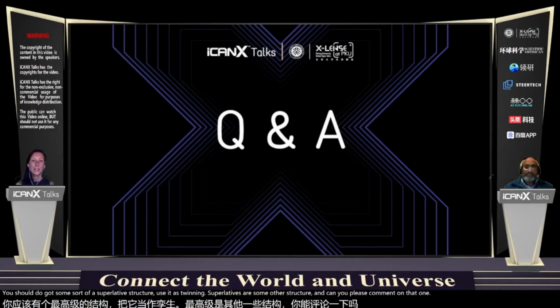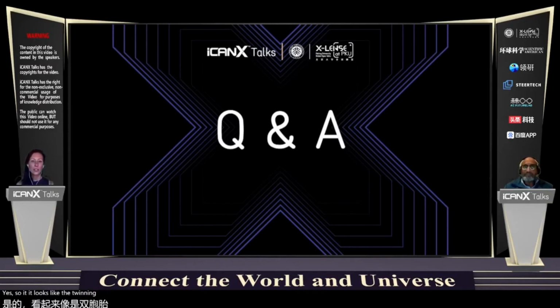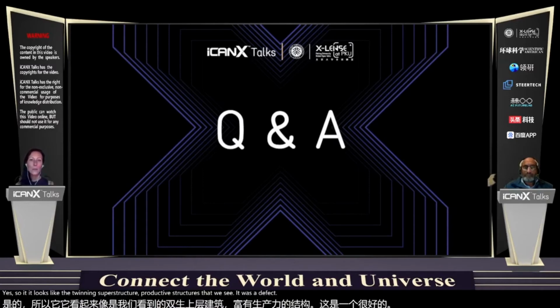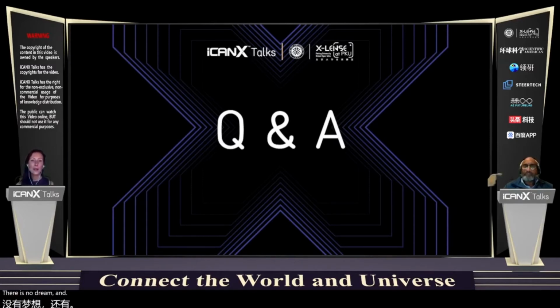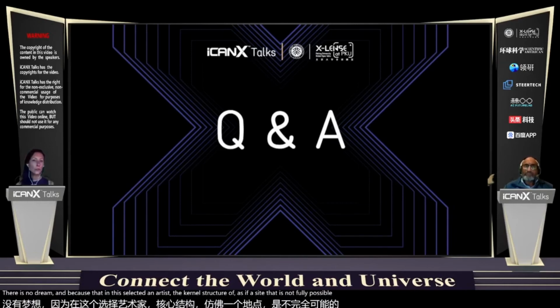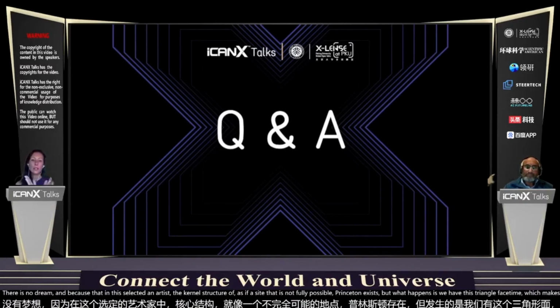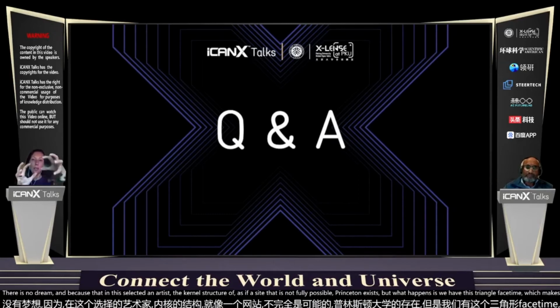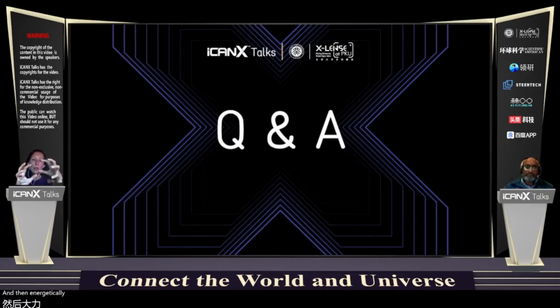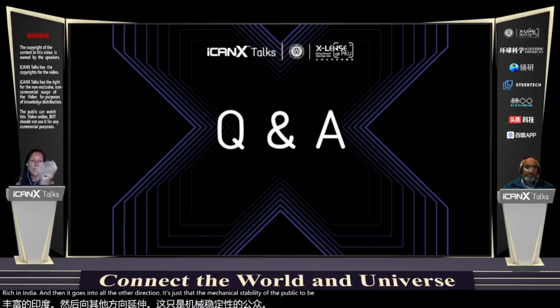Yes, so it looks like the twinning superlattice structures that we see with the III-Vs. There is no twin, because in this tetragonal structure of the zinc phosphide, there is no twinning possible. Twins don't exist. But what happens is we have this triangular facet, which makes the wire increase in diameter and the droplet becomes unstable. Then energetically, it's more favorable for the structure to just change the direction. And because it cannot twin, it creates a layer rich in indium, and then it grows into the other direction. It's just the mechanical stability of the droplet that creates this change every so often.